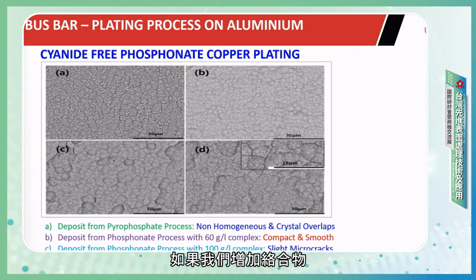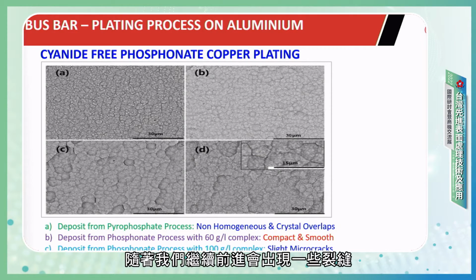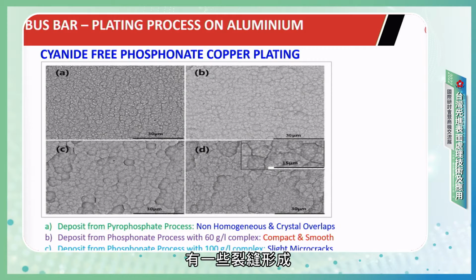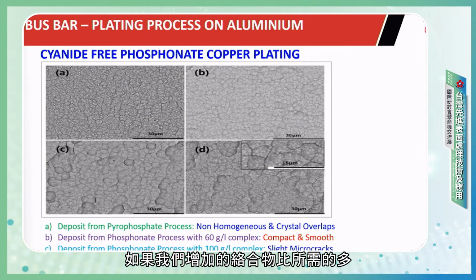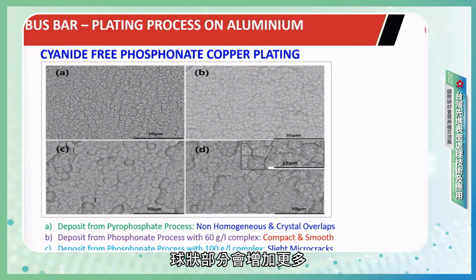If we increase the complex, you can see some cracks develop. As we move on, more crack formation takes place, and the deposit becomes coarser. You have seen in the earlier slide some fine grain with globular morphology. So if we increase the complex more than the desired level, the globular part increases more, making the deposit coarser, and also forming some crack patterns.